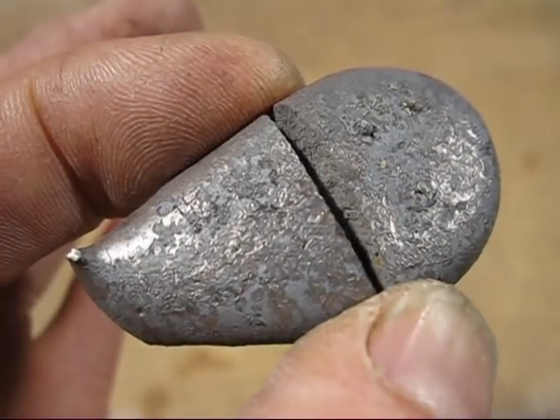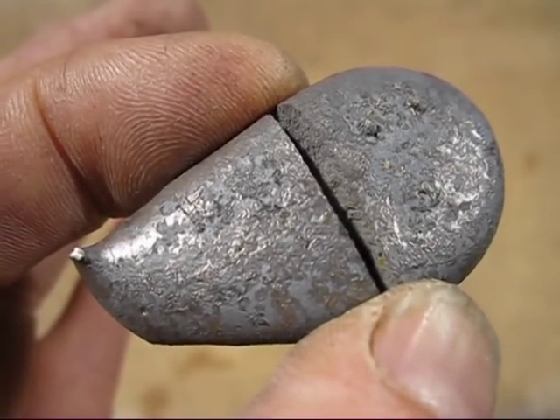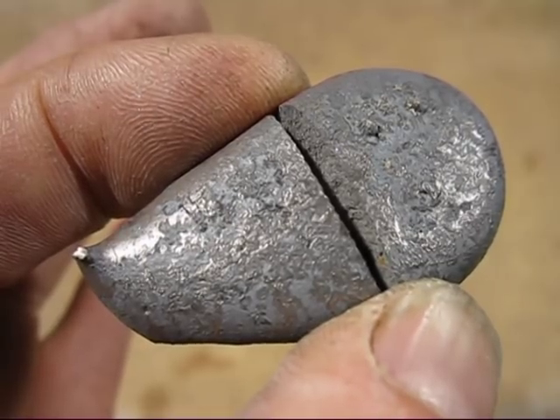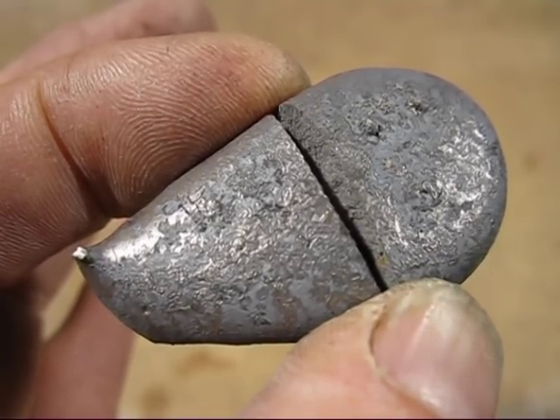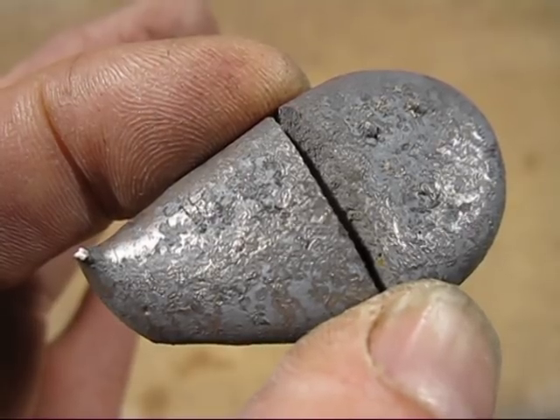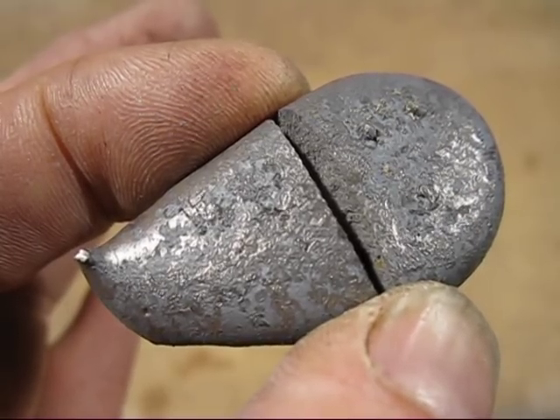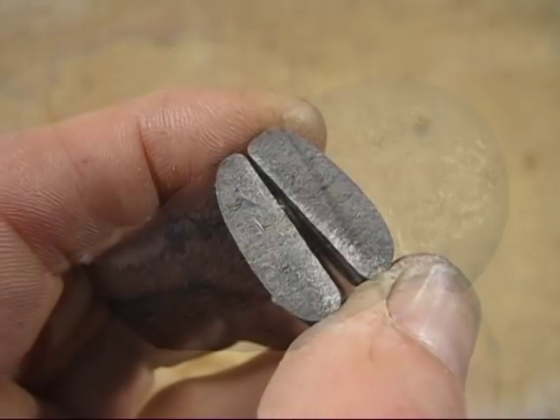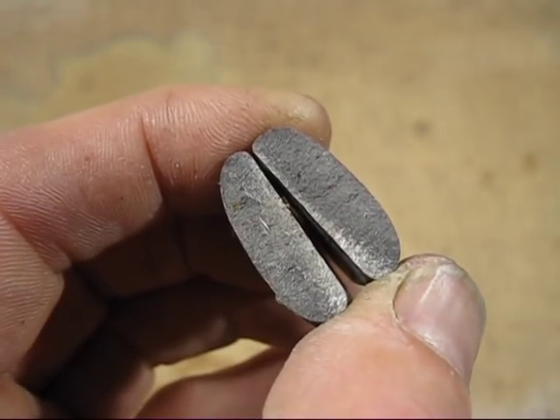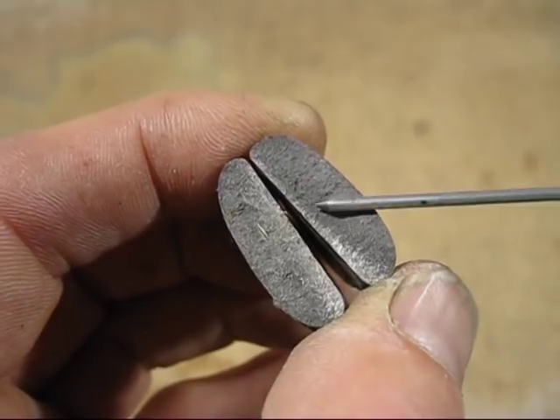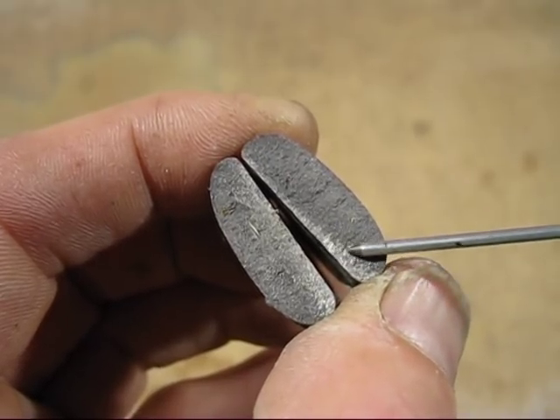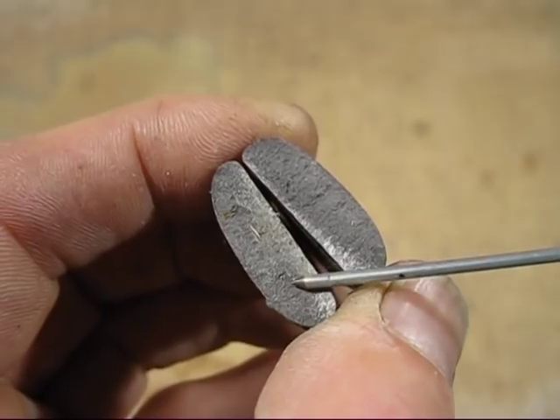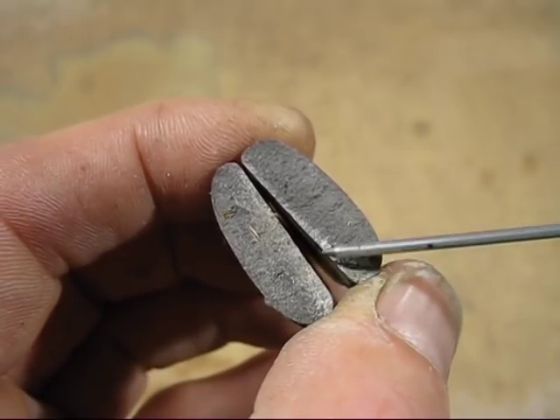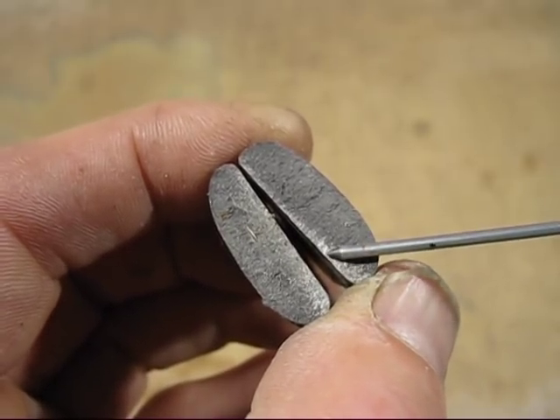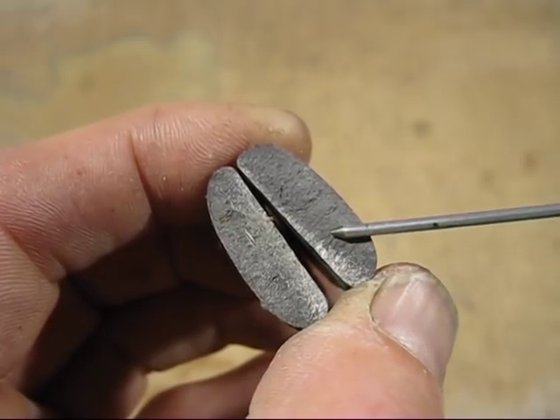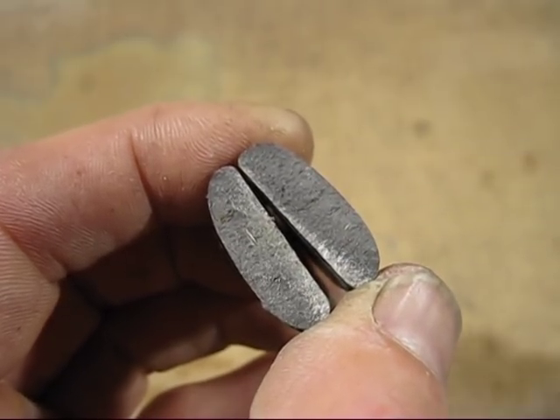This is the metal that I spilled while doing the wedge test. What makes this interesting though, it's spilled onto the cast iron mould weight, which is 20mm thick. So I've broken it in half and I'll show you what it looks like inside. It's white, just a little bit there, and the rest is grey. That is a really good example of soft iron, because normally if I spill it on the mould weight like that, it'll chill and it'll be white all the way through that iron.